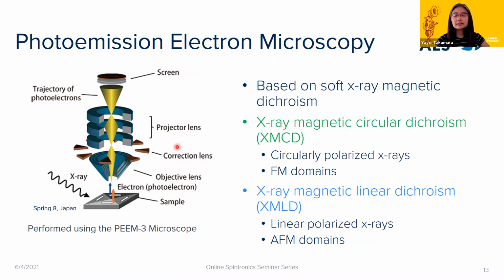We use the one at the Advanced Light Source. That beamline has the ability to change the polarization of the X-rays, from circular to linear polarized X-rays, so that from one location we can image what the ferromagnetic domains are, as well as what the antiferromagnetic domains are, if they happen to coexist in one sample. And if I've got a multilayer structure where, say, a manganese-containing layer is the magnetic layer and an iron-containing layer is antiferromagnetic, we can separate out the contribution from each layer, because the magnetic spectroscopy is element specific.